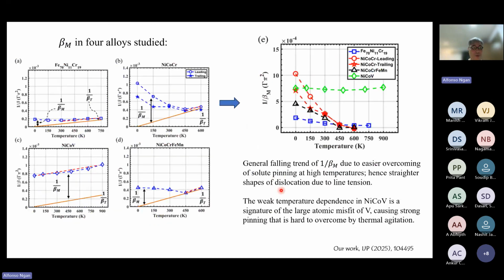For other alloys where the pinnings are weaker, we have different variation of the mean energy with temperature. So some may drop before it rises. This one we have seen before. The rise is pretty linear. Some stays constant before it rises. So it depends on the strength of pinning in the alloys.